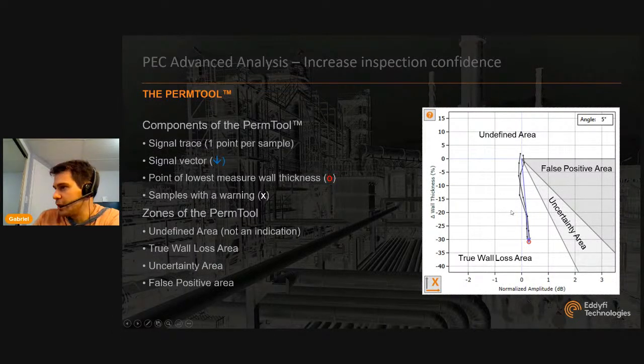And then there are different zones of the PERM tool. So depending on where the trace and the cursor are pointing, we're either seeing a true wall loss indication. So that's going to be typically a vector or a trace going straight down or slightly to the left if it's a near side defect. You'll go into the uncertainty area if the defect has a signature that is similar to that of a real indication or a false positive, and pointing into the false positive area if it's typical of a false positive indication. We've got this undefined area. So because we're pointing to the point of lowest wall thickness measurements locally, the vector is never going to point into that area. If the trace goes into there, then it's not characteristic of either a defect or a false positive. It's something else going on.